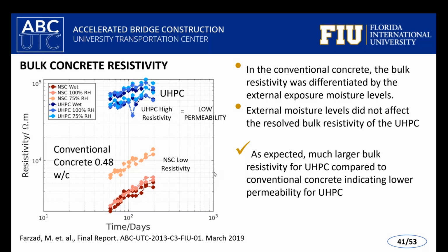So the peach and maroon colors are for a conventional concrete. You notice the resistivity is much lower than those of the blue and the purple UHPC materials. So evidently we know UHPC is a very high quality material, with a high resistivity. High resistivity relates to low permeability, and also less coupling of those electrodes required for the corrosion process. Also notably, we see the conventional concrete is dependent on moisture. So when you have dry environments, you will have a much higher resistivity, but still fairly low. When it's wetter, the resistivity will be smaller.